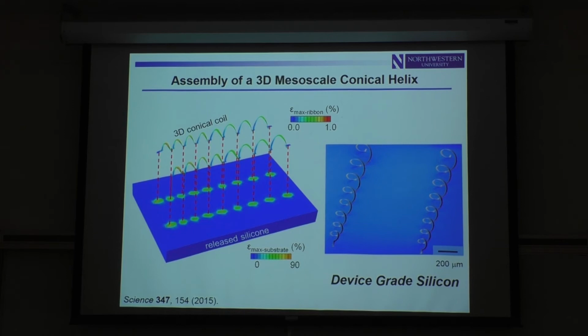That becomes a critically important design tool, but in this case, it allows us to map quantitatively the strains in these filaments and in the underlying silicone substrate, and here's a colorized SEM of the results of that process. So a pair of these conical 3D coils in device-grade silicon, and this could have any kind of electronic functionality built onto it, predefined before the geometry transformation. But we just show examples in silicon just so you can get a sense of it.